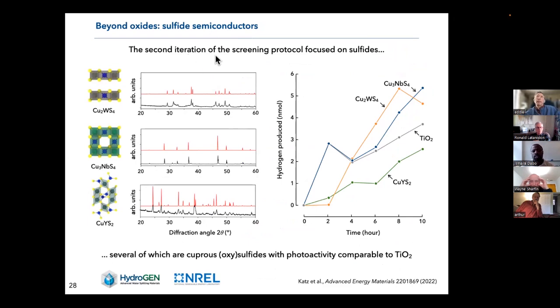So this is a second iteration of the screening protocol that focuses not on oxide, but on sulfide materials. So we can look at sulfide semiconductor. So we identify 3 of them, and they are very interesting transition in their structure from layer structure to something that is much more bulk-like. And you can see that in that case, those materials exhibit hydrogen production at a level that is comparable to some of the reference materials in the field of photocatalysis. So we're very happy of this progress.